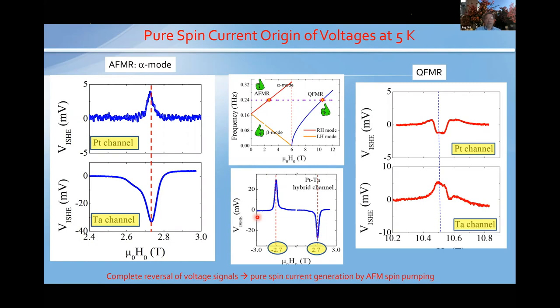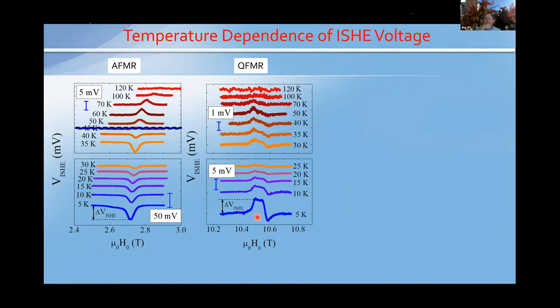Okay, if we look at the temperature dependence, it's even more interesting. Let's start with the low temperature feature. At 2.7, as I mentioned earlier, it is negative. But for the quasi-ferromagnetic resonance, I'm just pointing to the main feature; I think the other feature is something else. Let's say the main feature is positive, as our internal reference. We know that this has to be from the right-handed magnon. So if, using this metal, maybe tantalum, we have positive for right-handed, then here what happened? We have a negative signal.